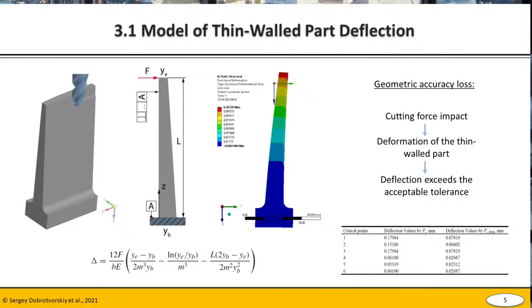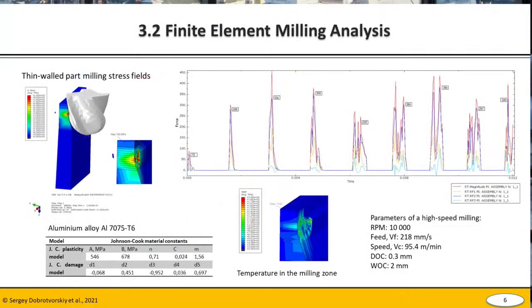Next slide, please. To perform the dynamic high-strain analysis, we used Johnson-Cook plasticity and damage criteria. It's empirical and represented by specific material constants. The analysis allows getting the force components acting in different directions, including the direction of minimum stiffness of the part. And nine bursts of the force response can be observed on the graph. Each corresponds to cut in and cut out of a cutter tooth. Additionally, the maximum indicators of the component that reacts in the deflection of minimum stiffness are highlighted. Also, we found that during high-speed milling, heating does not cover the entire thickness of the investigated sample. Next slide, please.